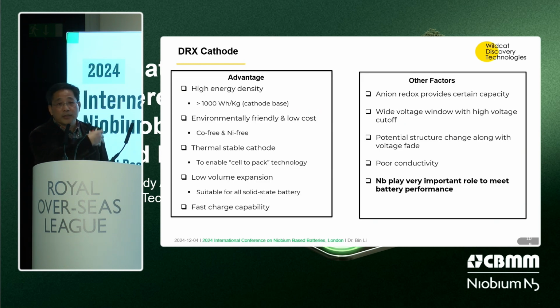So as a summary, for the DRX, it has very high energy density, and it's cobalt and nickel free and more stable, which gives you much advantage in terms of pack energy density. That's why LFP can challenge the NMC, because the pack energy density could be getting close to the NMC. And also low volume change and faster charge capability. We do see niobium plays a very important role. Thank you for your time.